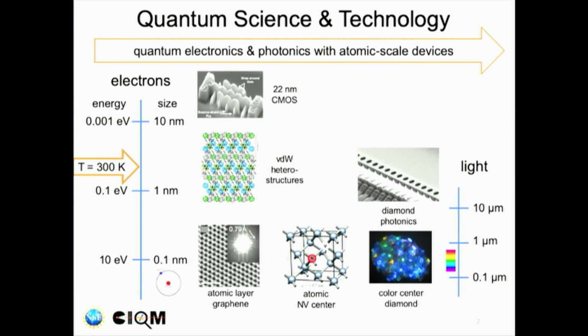But when you go down to graphene, you're near the size of a hydrogen atom, and the energy goes up to 10 electron volts, which is much greater than room temperature. And so using these materials, you can develop a device that's entirely quantum and that works at room temperature. And that's a very different game than developing regular electronics.